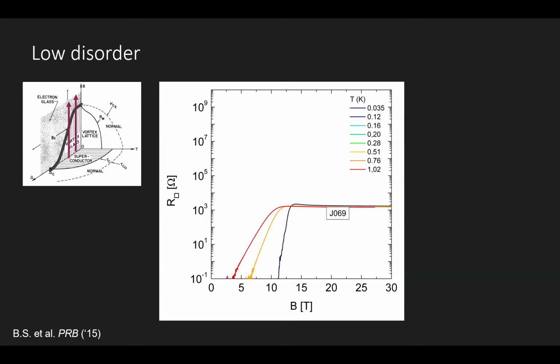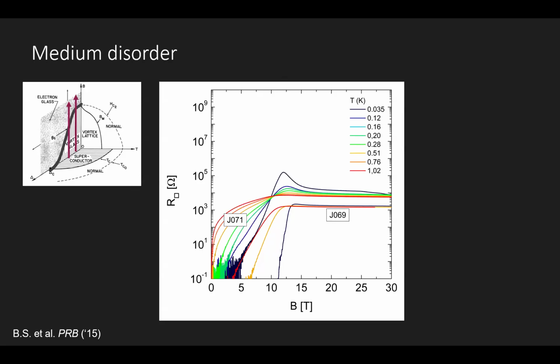Now, if I increase the disorder in this material, what happens is the following. The resistance is increasing substantially, and surprisingly, the critical field is decreasing to lower magnetic field, which is opposite to what we know in standard superconductors, because usually when you increase disorder, Hc2 increases. And most importantly, you have a peak of the magnetoresistance that appears just at the transition to the normal state.